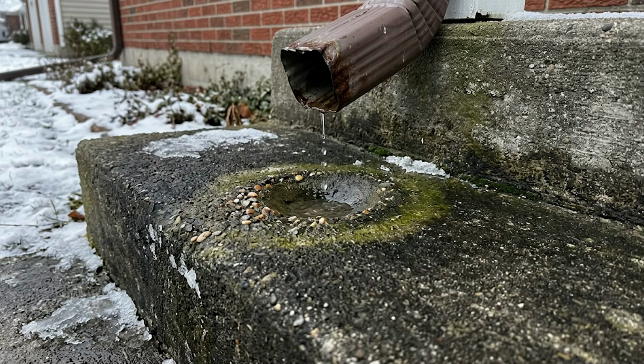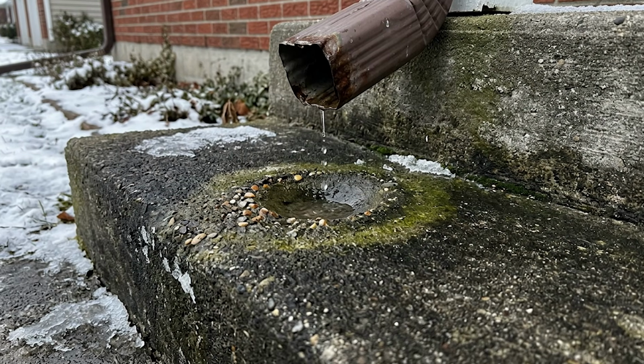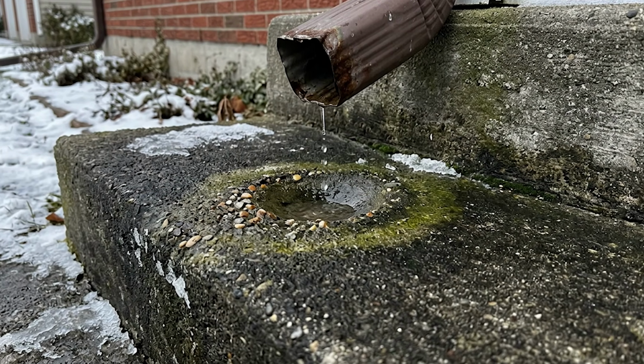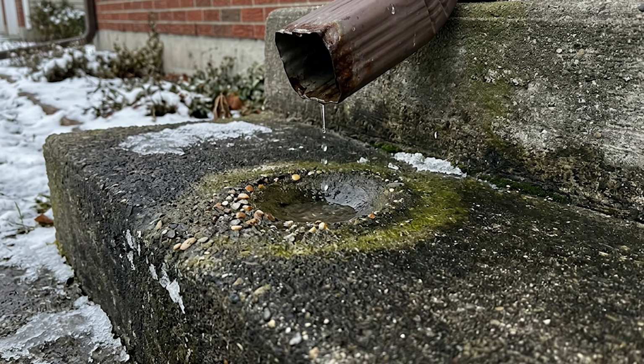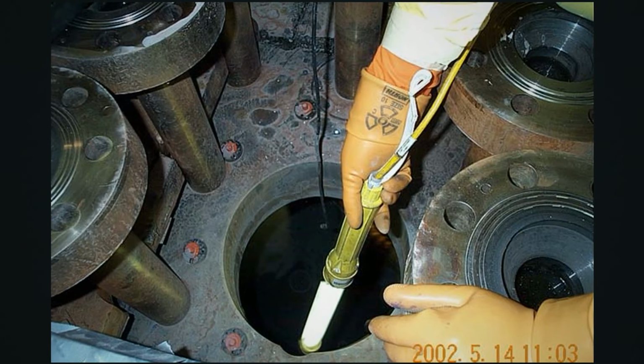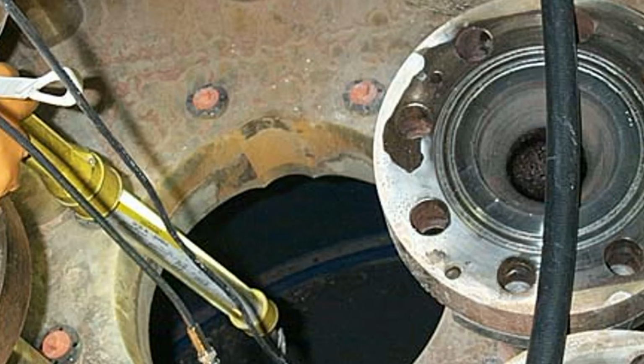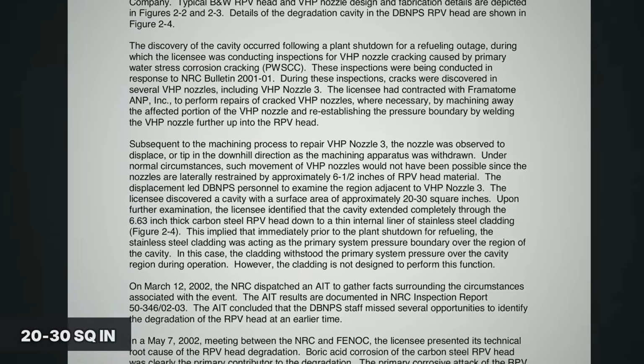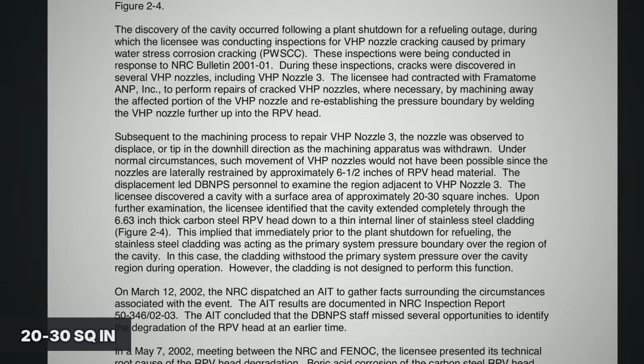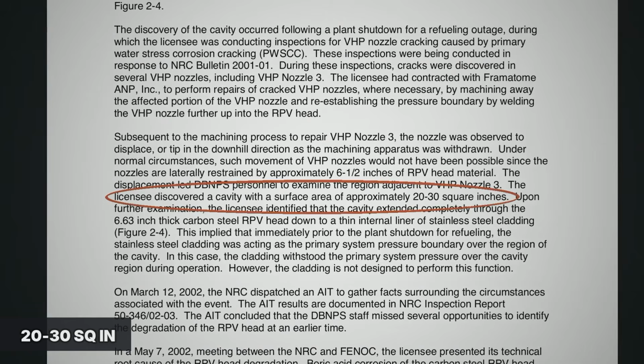It cores. Think about a drip from a gutter joint hitting one spot on a concrete step for 6 winters. You do not get an even wear across the step. You get a hole where the drip lands. Same geometry here. The leak path fixes the location, and the location gets eaten while everything around it stays mirror clean. Down it goes, through 6.5 inches of carbon steel. The cavity that was eventually mapped ran roughly 4 by 5 inches at the base and opened wider toward the top surface. Something on the order of 20 to 30 square inches of missing structural steel, described in the Government Accountability Office's report as pineapple-sized.